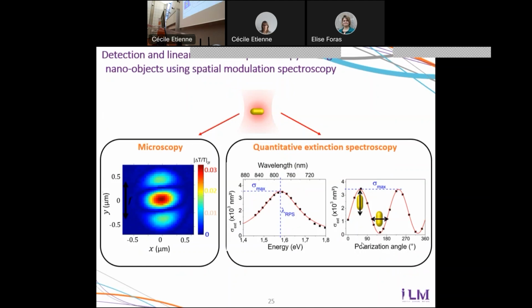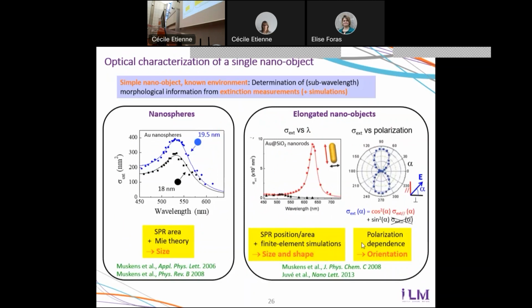So with this tool, we can, for instance, determine optically the orientation of a single nano object, even if the optical resolution does not allow us to really see the shape of the object on the image. So measuring quantitatively the optical response is actually very useful for us because it means that even if, as I just said, the optical resolution does not allow us to see directly the shape of the objects, we can actually deduce information about the shape and size of the objects that we study just from their extinction spectra that we measure.